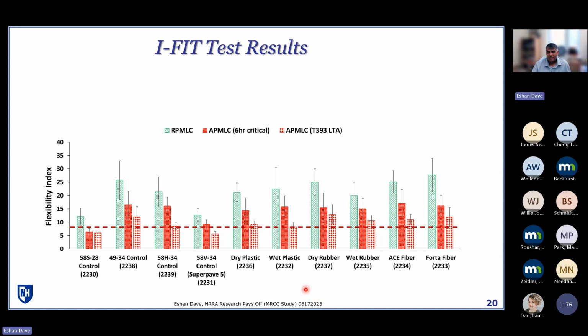The other observation I saw is that there was not really too much distinction. In other words, if a mix had a certain amount of drop going from reheated to the critical aging, that mix continued to degrade further with the Illinois DOT's aging procedure. So there was no discrepancy, in other words, where a mix all of a sudden did not show as much aging related degradation with that more severe aging as it had with, let's say, an intermediate aging. So that's good because they are all consistent.